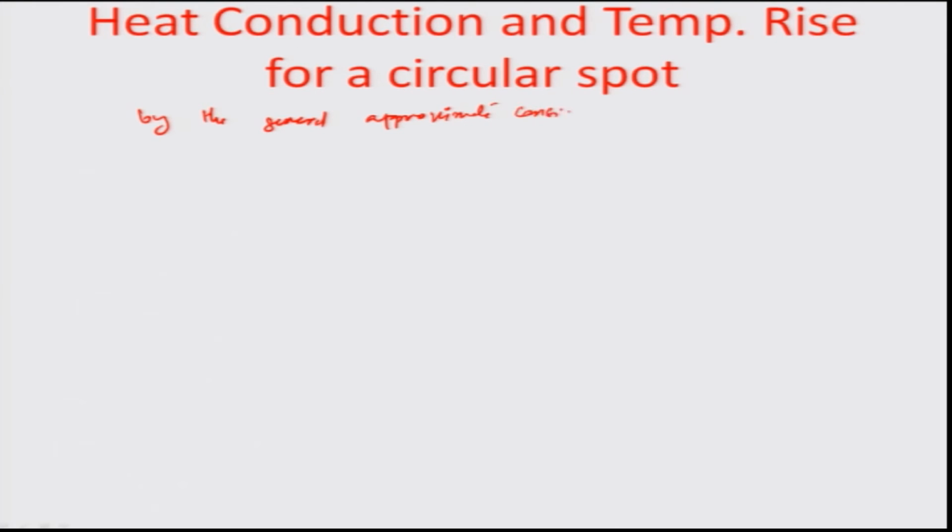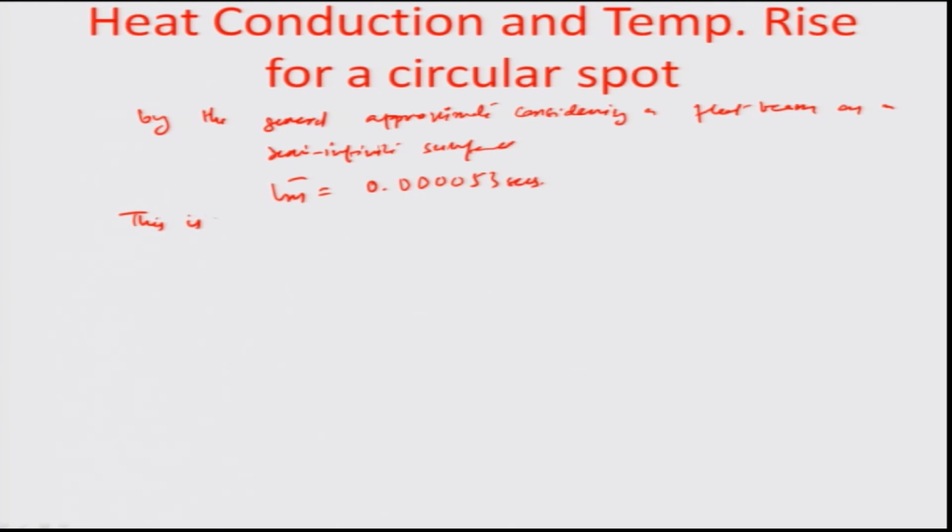Considering a flat beam on, let us say, a semi infinite kind of surface, the total time scale which we actually saw was very small, 0.000053 seconds. This is quite different than the more accurate expression arrived at with circular boundary condition.